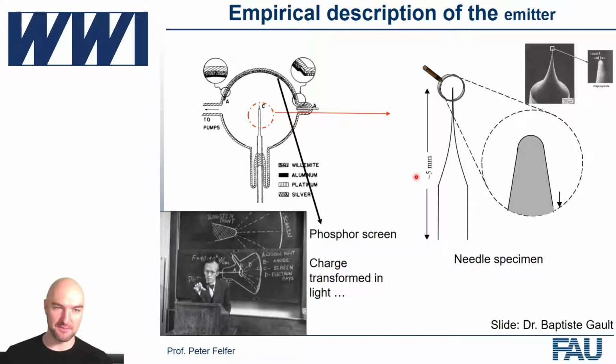And so the most central thing for us is looking at the field emitter. And we're doing it a little bit more in detail in the next session. Essentially, the field emitter is just some kind of needle with a very small radius. And if you derive the field on the surface of a charged sphere, you will see that it's just simply voltage divided by radius.